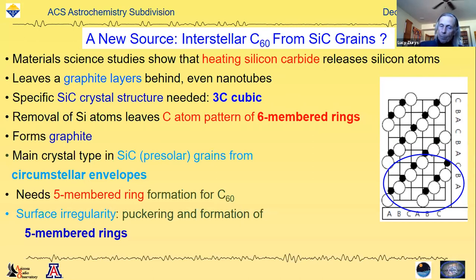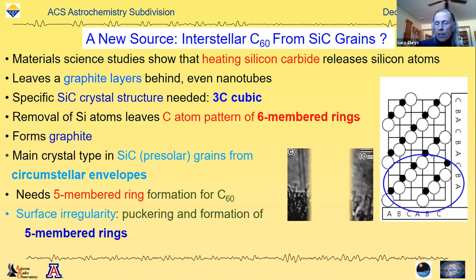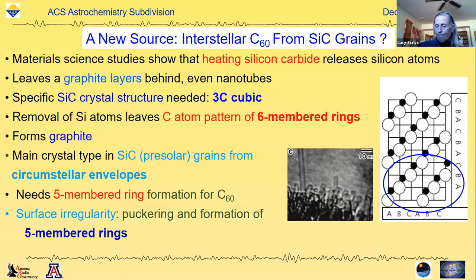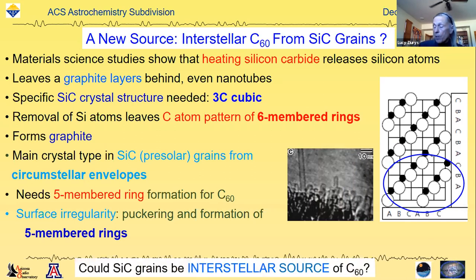And we know that because people study meteorites and extract these grains from the meteorites themselves. By looking at the isotope ratios, they know they're from circumstellar envelopes, and that's the crystal structure in them. But to form C60, you need to form more than 6-membered rings. You must form 5-membered rings. And it turns out that if you have irregular silicon carbide grains and you heat them, the surface irregularities will cause the graphite sheet to pucker, okay? And they've actually seen formation of nanotubes and nanobuds from silicon carbide.